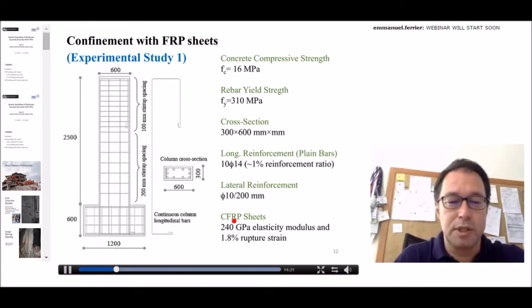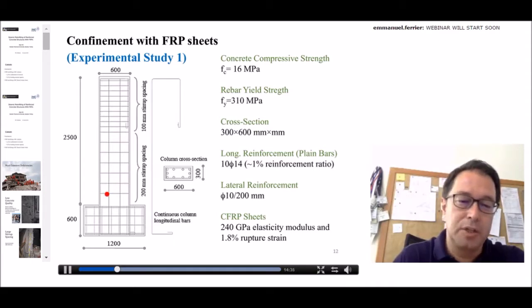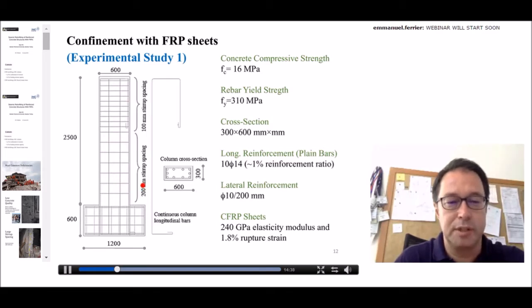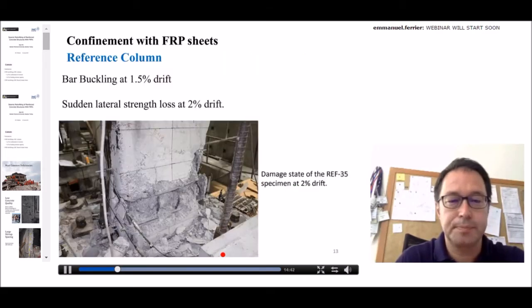And for retrofit of these kind of substandard columns, we use CFRP sheets with the characteristics given here. I should say that we have no overlap bars for those specimens, just to eliminate potential effects that could change the behavior. So we don't have any problems about lap splice deficiencies or lap splice lengths.